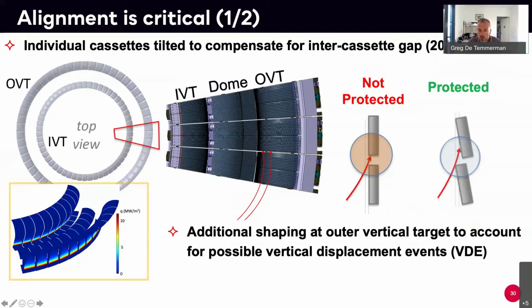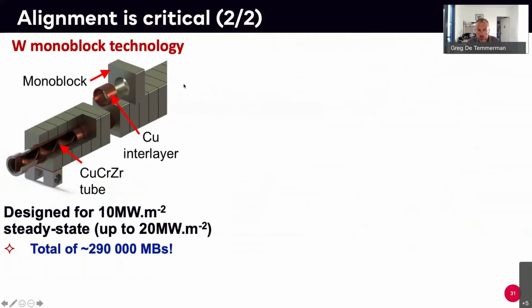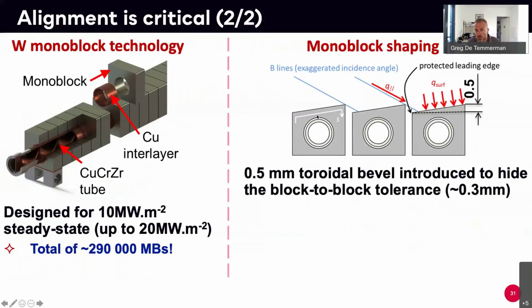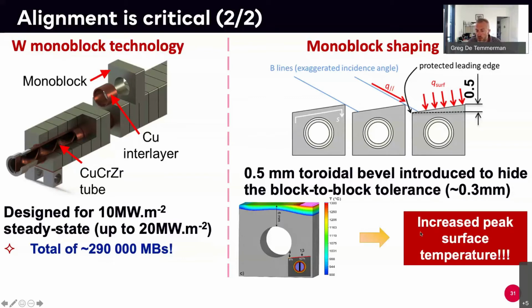But even more, when you go at the level of the monoblocks, so these are those tubes that I showed you, each of those monoblocks has to be beveled with a 0.5 millimeter height difference between one side and the other. So this is strongly exaggerated here, but for the same reason, so that all of the blocks have their edges protected. So you can never have a plasma penetrating inside a gap at normal incidence. So the tolerance for such a piece is about 0.3 millimeter in that direction. So you have to have a very precise alignment, and then you shape the surface of all those blocks to actually protect the leading edges.